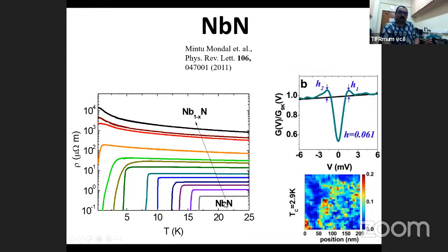So you have this niobium nitride, and here you can increase disorder. Niobium nitride has a very simple crystal structure, the crystal structure of sodium chloride, your common salt. And what you can do is have more and more vacancies in the niobium nitride crystal structure. They act as scattering centers, reduce the mean free path, so that's a way to increase the defect.